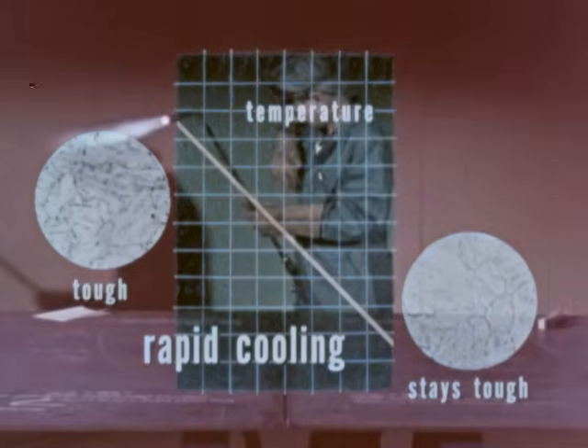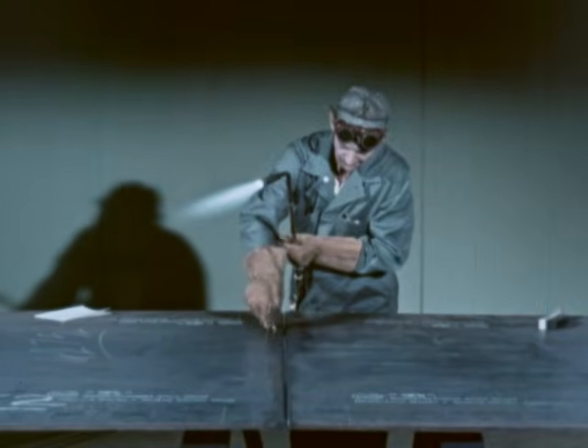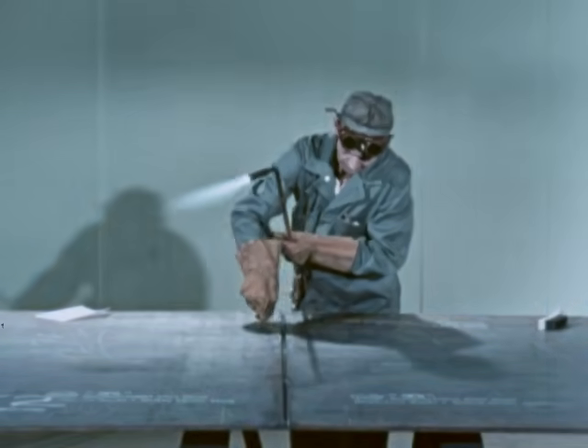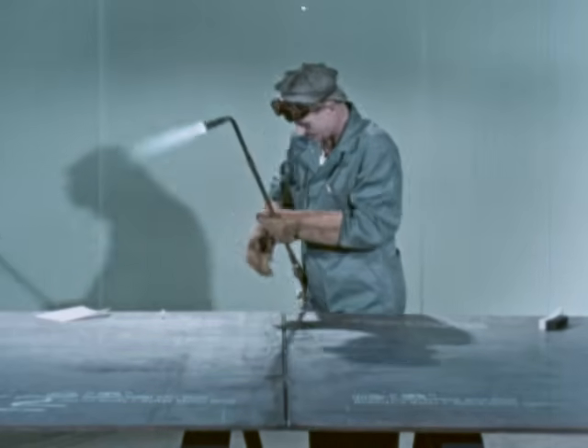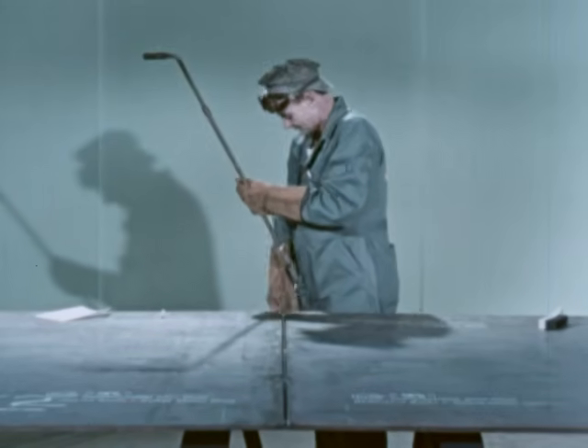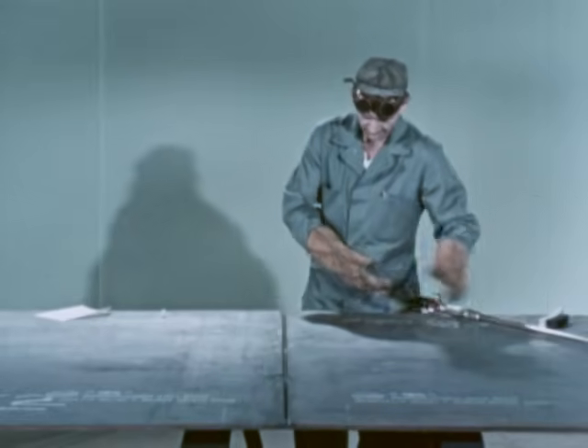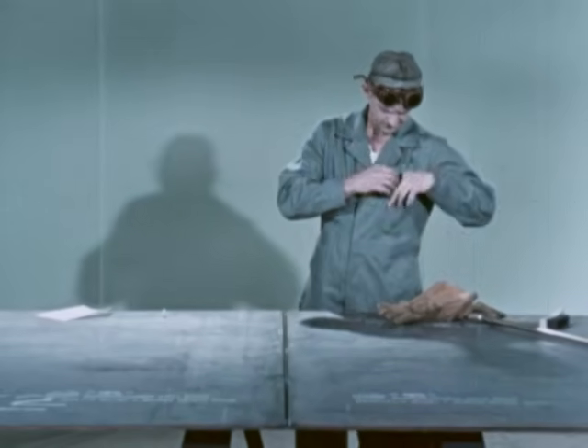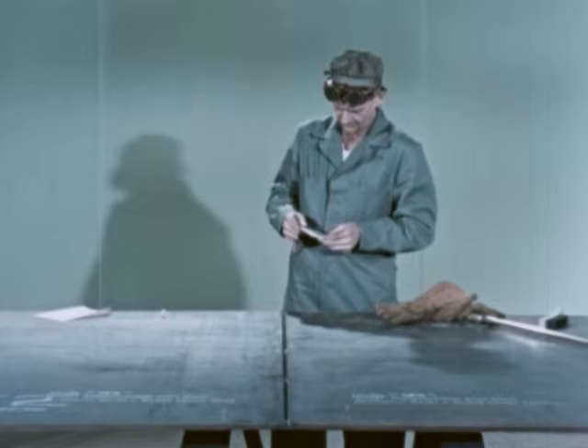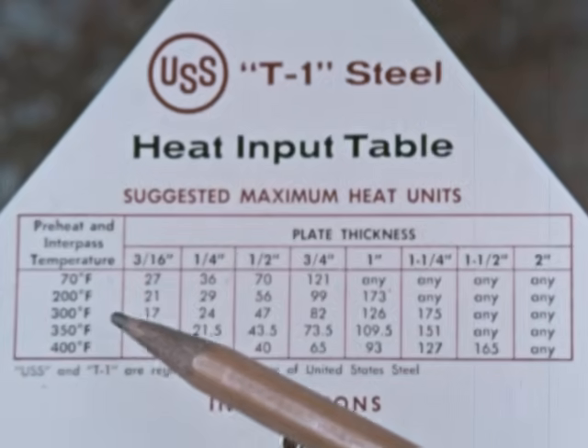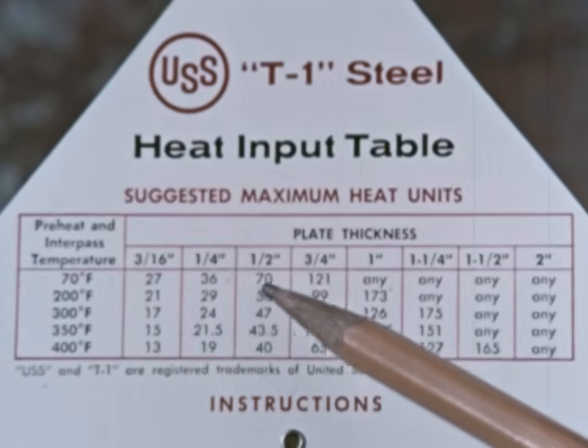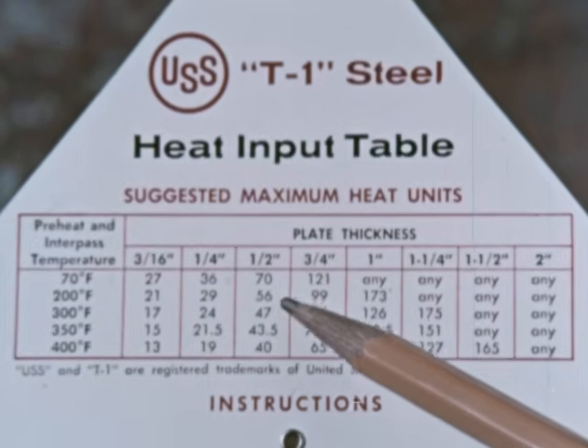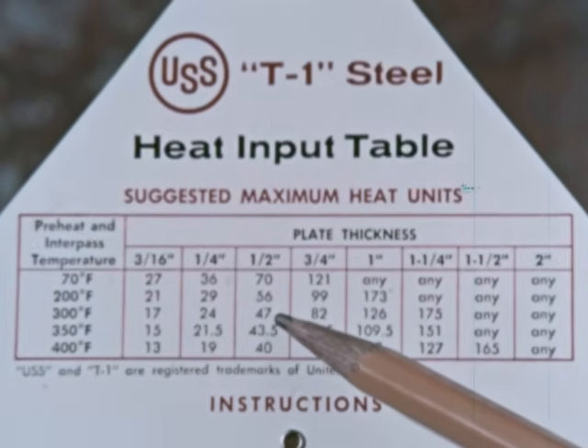Suppose we illustrate with a job that might come your way. You want to butt weld 1/2-inch plates. Assume that we use a preheat or interpass temperature of 300 degrees Fahrenheit. You check the table on your calculator. It tells you that at 300 degrees, 1/2-inch plate has a suggested maximum heat input of 47 heat units.